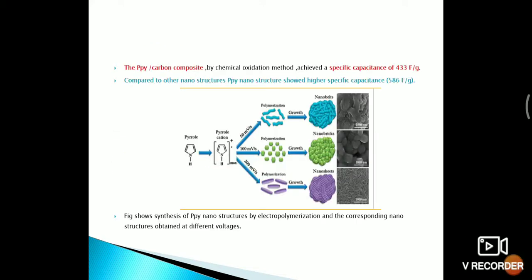The polypyrrole carbon composite by chemical oxidation method achieve a specific capacitance of 433 farad per gram. Compared to other nanostructures, polypyrrole nanostructure showed higher specific capacitance of 586 farad per gram. This figure shows a synthesis of polypyrrole nanostructures by electropolymerization and the corresponding nanostructures obtained at different voltages. These nanobelts, nanobricks, and nanosheets are the different nanostructures of polypyrrole and obtained at electropolymerization of 50 millivolt, 100 millivolt, and 200 millivolt voltages.